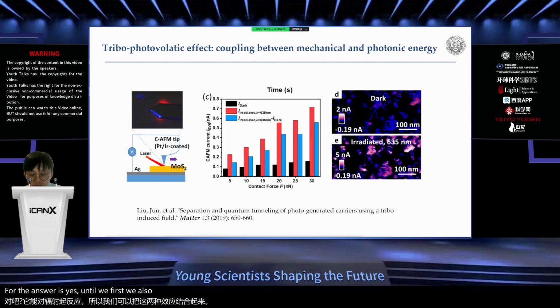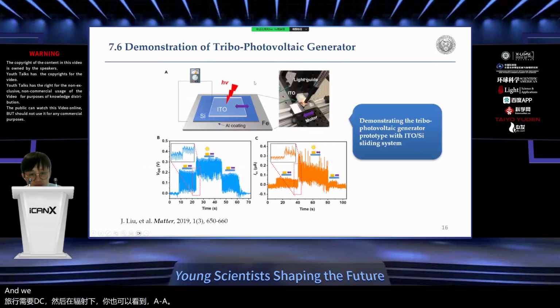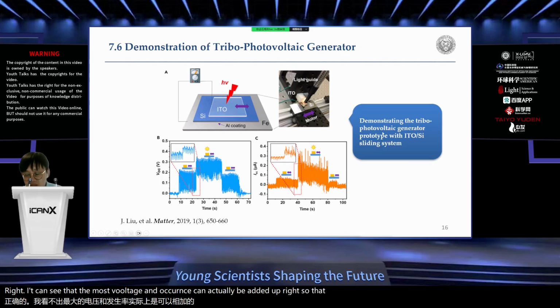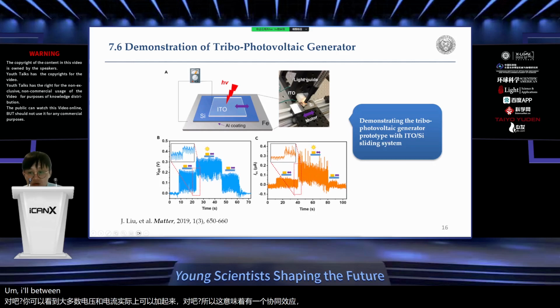So we also did the irradiation experiments in the AFM system, and we did observe an adding up of the current outputs with and without irradiation. And we know that without light, it does give you outputs, which correspond to the tribovoltaic DC. And then under the irradiation, you also see outputs. And then we also demonstrated it with silicon at the macroscopic level. So here we demonstrate the idea with sliding ITO on a piece of silicon. We know ITO is a transparent conductive oxide, right? And you can see that both voltage and currents can actually be added up, right? So that means there's a synergetic effect between the tribovoltaic effect and the photovoltaic effect.